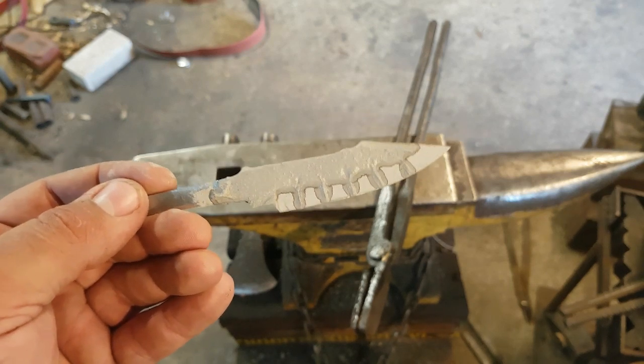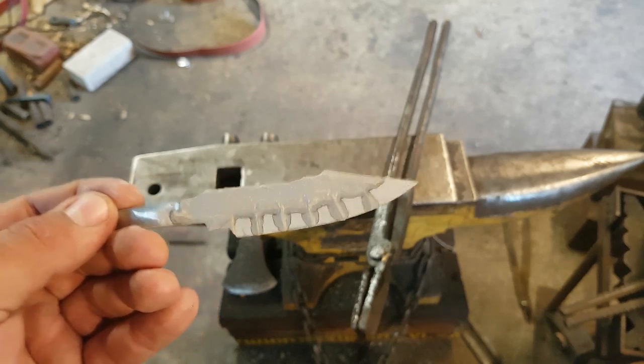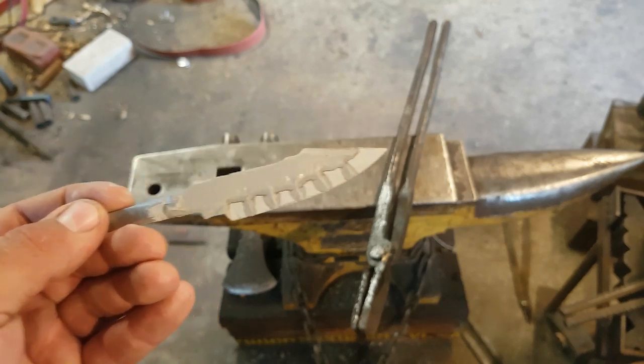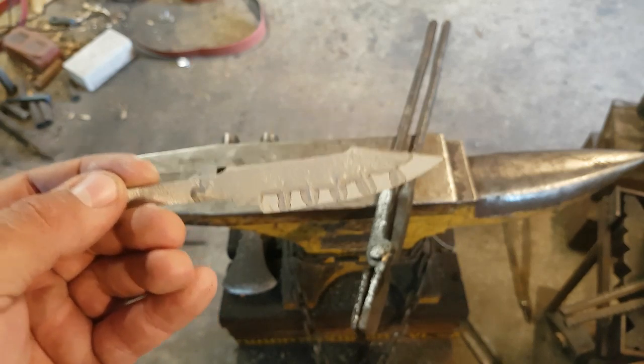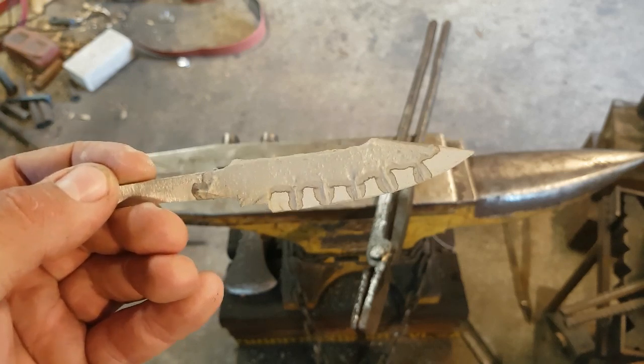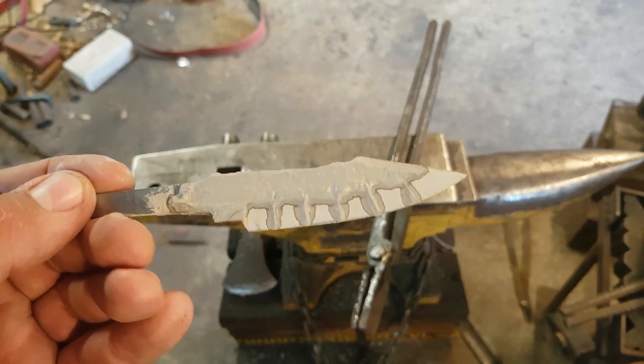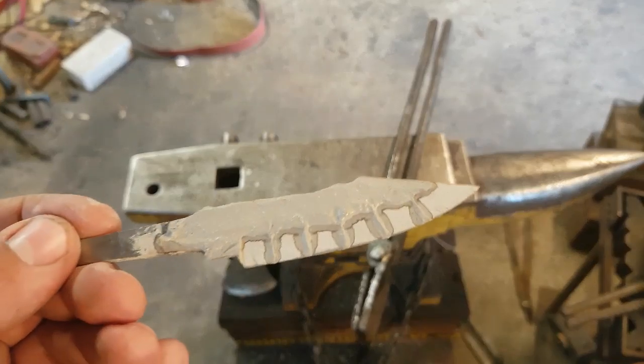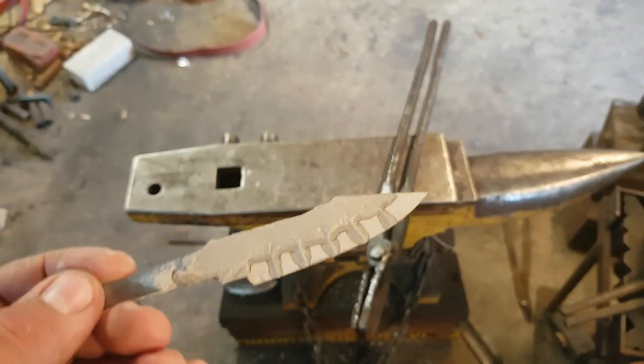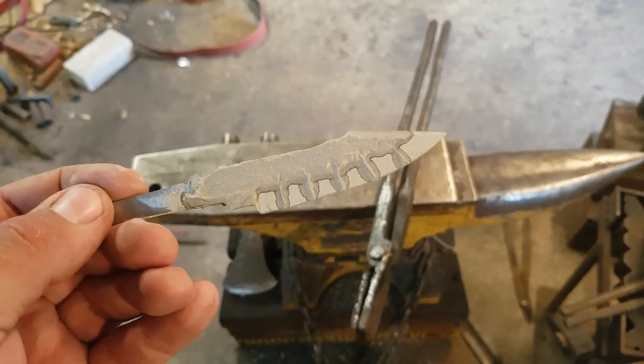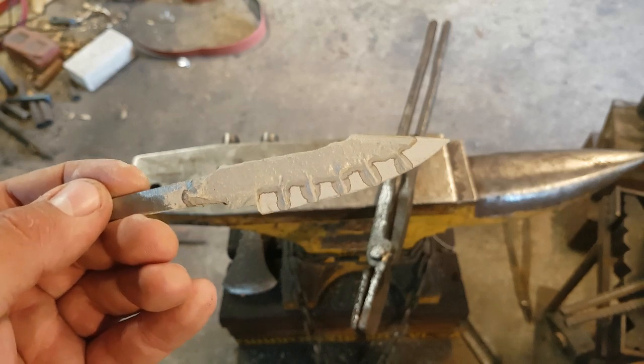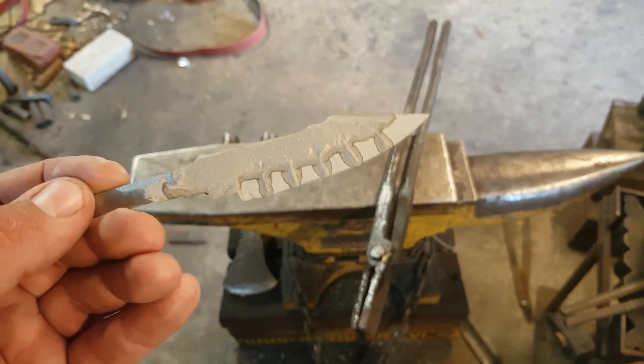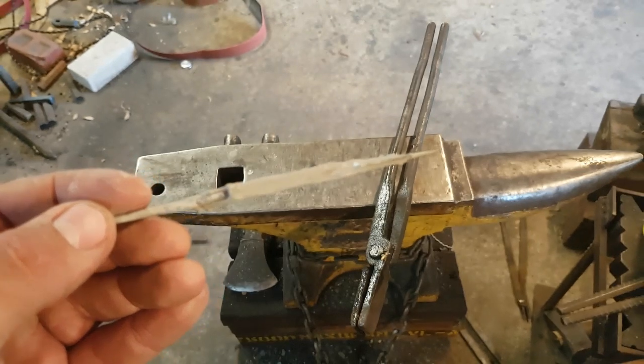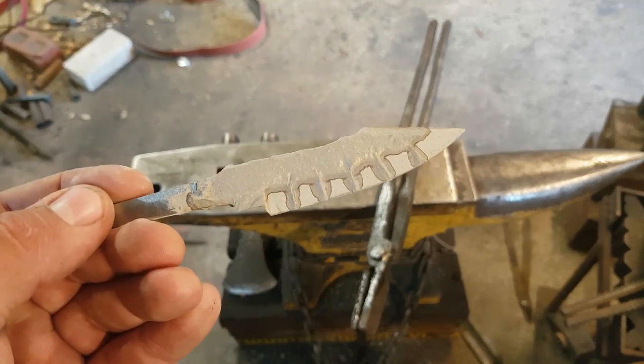You could just let it dry in again until it's tacky like the underlayer, and then slowly heat it over the charcoal forge, or slowly hang it in front of the gas forge, flicking it back and forth to slowly dry it out. What you don't want to do is try and dry it quickly, because what will happen is the clay will immediately pop off. But once this is dry, tomorrow I'll come back and we will quench this thing.